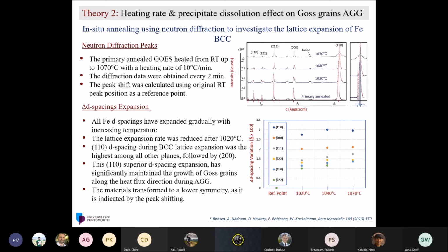So when you look at the delta D spacing, in the lower graph I'm showing not the D spacing itself but the variation of the D spacing of the lattice plane. Of course, it is standard and well established that by increasing the temperature, the D spacing will elastically expand. That's understandable. However, the 110 expanded much more than the others, followed by 200. This is again understandable from the crystallographic point of view.